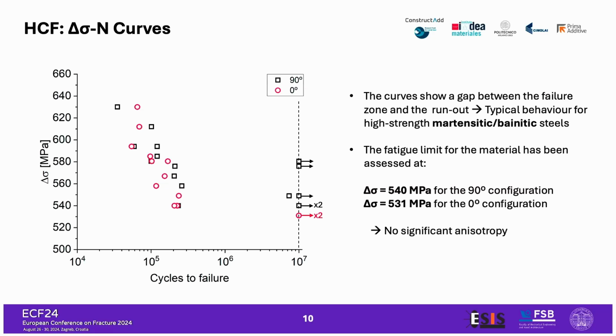So there is almost no anisotropy also in the fatigue properties, because due to the limited number of test specimens and so limited statistics, we assess the fatigue limit at 540 and 531 megapascal of delta sigma for the different configurations. But again, it's also due to the limited number of available specimens. So if you look at the points, actually, we can say that the material behaves basically the same way between the two configurations. Now, this is a material property.